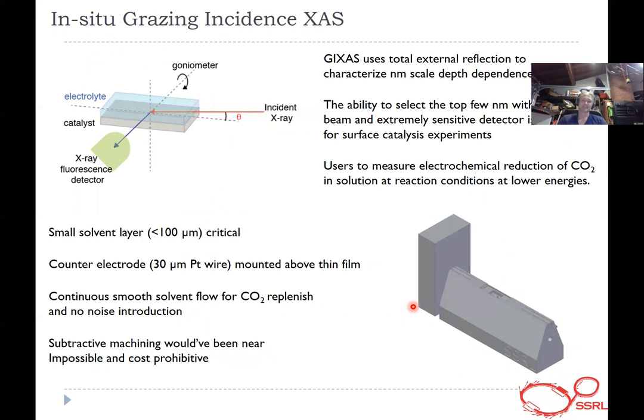We've used it extensively. We designed an electrochemical cell for reduction of CO2. So we look at the interface between the electrolyte solvent and the catalyst surface as a function of potential. So we apply a potential to that. The limitation for this is we have to have an extremely small solvent layer because we have to get X-rays in and out, and at a grazing incidence, your path length gets really long.